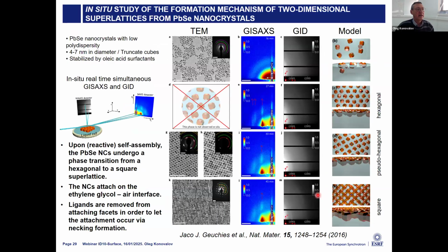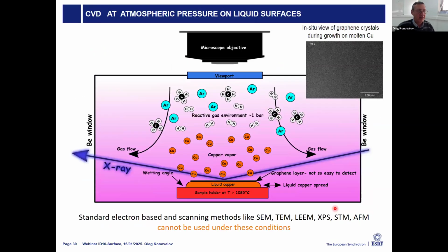Here we apply GISAXS and GID measurements simultaneously to characterize the growth of 2-dimensional crystals from lead selenide nanocrystals. With these measurements we were able to characterize and give a model of how the growth goes. Also, as this is an in situ measurement, we could find some other structures which it is not possible to find with electron microscopy, because you cannot pick up these crystals.